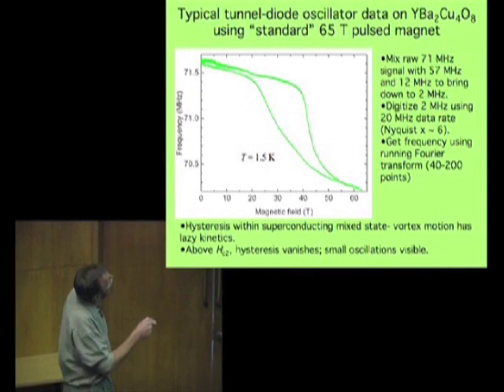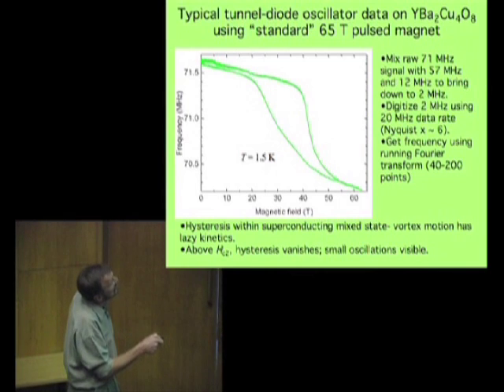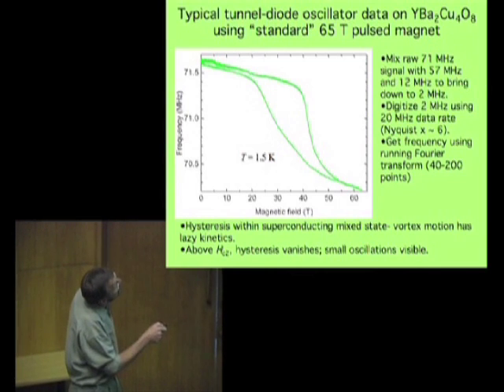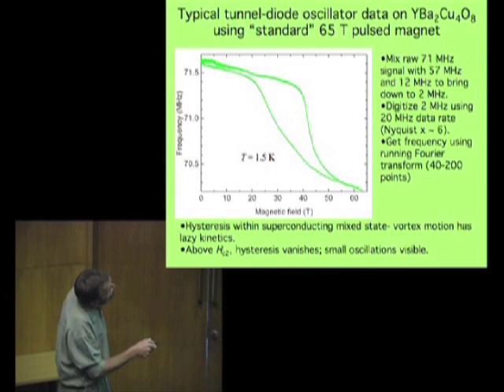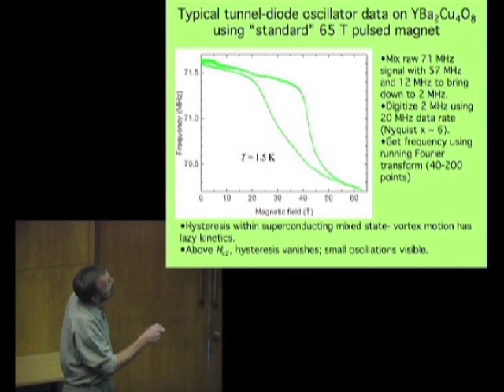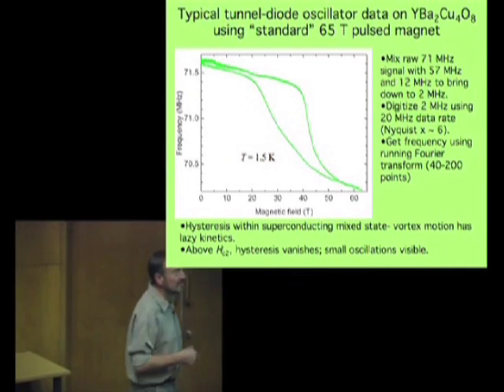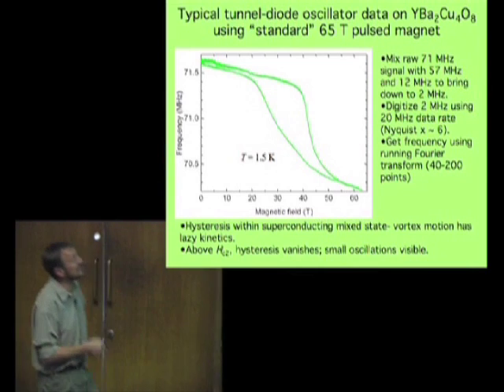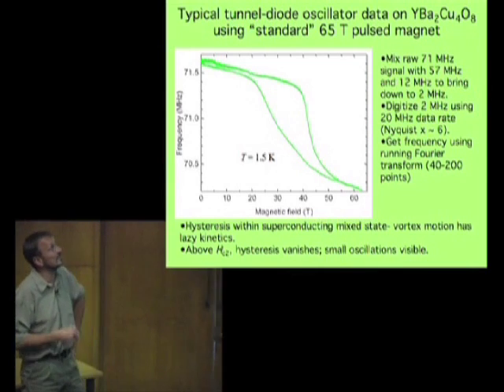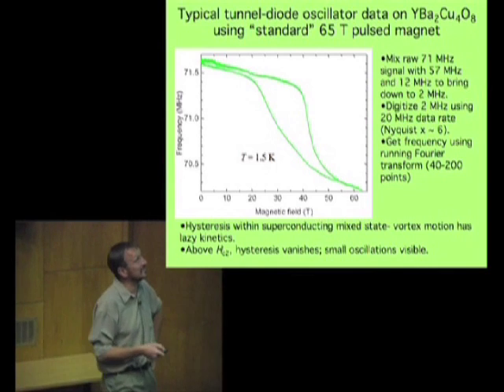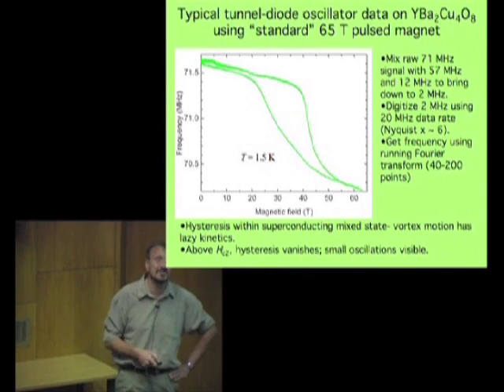What you notice first of all is this is frequency, this is magnetic field. We sweep the magnetic field up and the frequency follows one path, then it goes on to here. Then we sweep the magnetic field down, it follows the same path, and then the paths diverge here. The reason is that the vortex motion in high temperature superconductors is extremely lossy and has lots of lazy kinetics associated with it. It relaxes slowly.